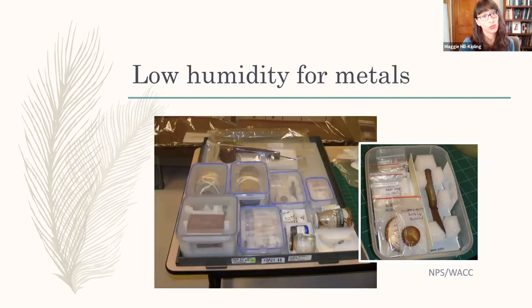Another place where you want to create microenvironments is often low humidity storage for metals. Some metals are extremely sensitive to humidity, particularly iron when there have been chlorides present, and they can drive their degradation anywhere over 15% humidity. So getting really low humidity in storage, much lower than you would want in the rest of your storage, can be really important.